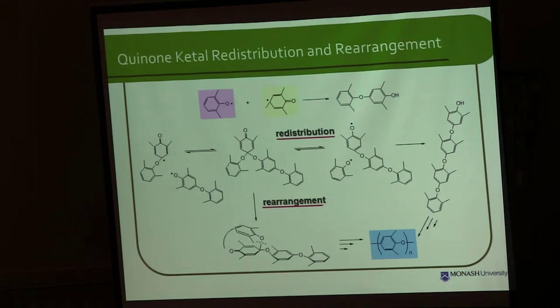At the same time, I focused on the polymerization of these phenols and found the redistribution mechanism, which is key for the polymerization. Redistribution polymerization is the coupling between oligomers, dimers, or phenols to increase the molecular weight of polymers. However, if you look at this reaction, it is an equilibrium reaction.